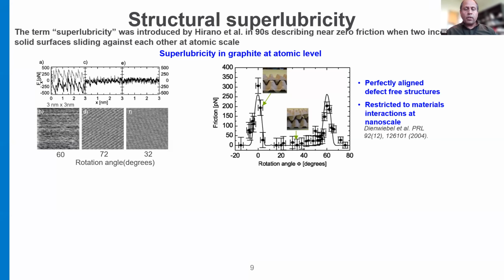It's not like superconductivity where the current reduces to zero, because in mechanical vibrations there are always going to be atoms that vibrate, so there is a finite amount of energy dissipation that always remains. The term superlubricity was coined by the Japanese scientist Hirano in the 90s. And then the first convincing experimental evidence, I think, was by the German scientist Martin Dienwiebel, where he showed graphite sliding against graphite. This is the AFM-like apparatus. And they were basically changing the angle of the graphite. What they found is that at a certain angle, or the magic angle, the friction reduces to a very, very low value, and what they called this is structural lubricity.